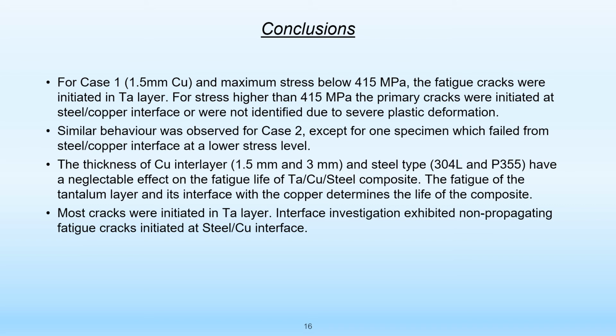The thickness of copper interlayer and steel type have a negligible effect on the fatigue life of the composite. The fatigue performance of the tantalum layer and its interface with the copper determines the life of the composite. Interface investigation exhibited non-propagating fatigue cracks initiated at steel-copper interface.